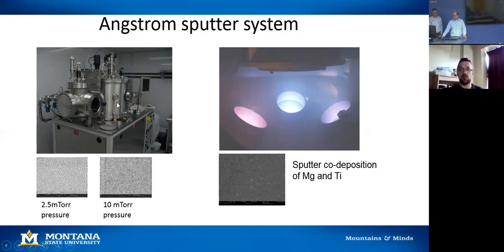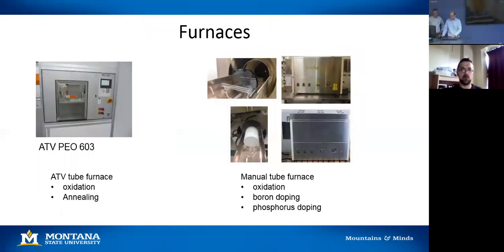This tool, again, just to go back to that structure zone diagram, you can see here this aluminum coating, and just by changing the pressure from 2.5 to 10 mTorr, you get a much different surface. It's probably not so easy to tell on the photograph. A little bigger, higher magnification on the electron microscope to see this more clearly, but you get a much different film. It'll have different conductivity and mechanical properties. Another example here is a sputtered co-deposition. We had two guns running at once for magnesium and titanium to make an alloy, and I'll discuss that a little bit later.